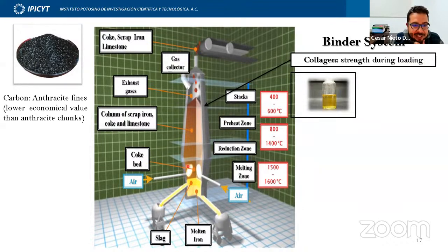Just to remind you, at the bottom there is a coke bed. When air comes inside the furnace, the coke is burned, and this is the heat source to melt the iron on top. And here is many tons of material: coke, scrap iron, and also some flux that helps the production of slag, like limestone and some other things. As the cupola furnace is a continuous production line, you always have flowing molten iron and molten slag, which means that you have to provide raw materials all the time while the furnace is operating.